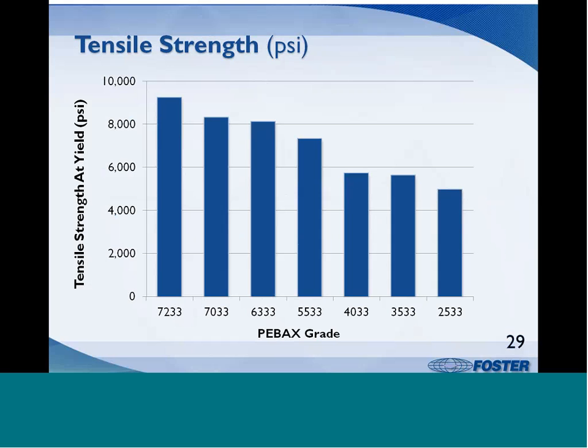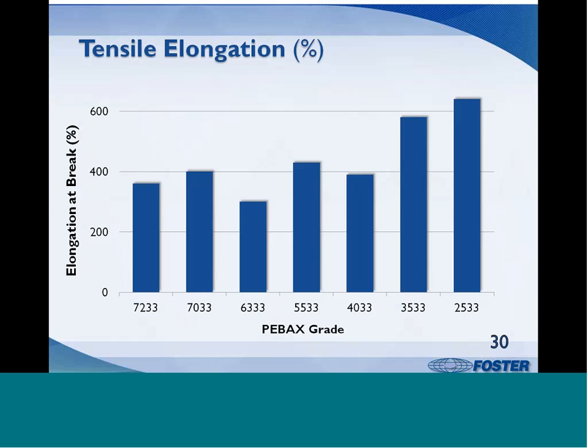When ultimate tensile strength versus grade is plotted, one can see how break strength increases with increasing hard block to soft block ratios. This is directly related to hardness. The harder the polymer, the higher the tensile strength. Graphing elongation at break versus grade shows that decreasing the hard block to soft block ratio leads to greater elongation and therefore flexibility.